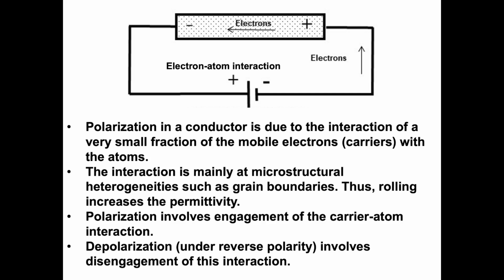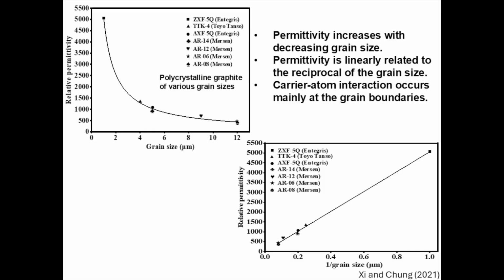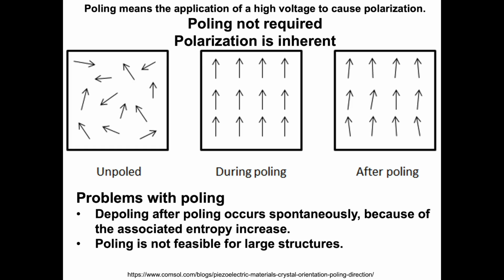And polarization involves engagement of the carrier-atom interaction, the carrier referring to the mobile charges, and depolarization under reverse polarity involves disengagement of this interaction. We varied the grain size of polycrystalline graphite, and indeed, the smaller the grain size, the higher the permittivity. And if we plot that versus 1 over grain size, we get a linear plot, indicating that it's the grain boundaries that matter in this carrier-atom interaction that's responsible for the permittivity.